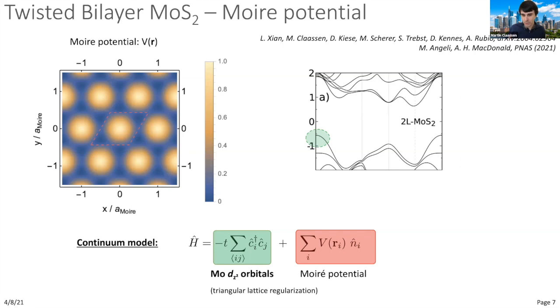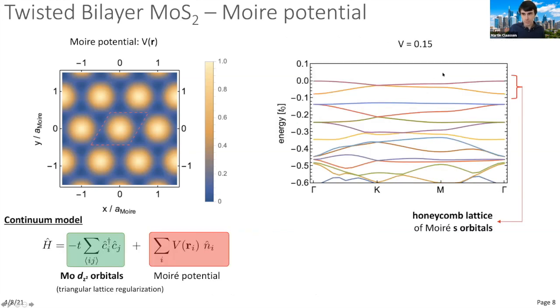This gives a route for more interesting things: what happens with more bands, and what happens when the potential is not scalar but matrix-valued or non-Abelian? For the scalar potential case—this was proposed in the context of cold atoms with optical lattices—as a lattice regularization of a continuum model, increasing the long-wavelength moiré potential strength forms minima on a honeycomb lattice. Electrons localize at the honeycomb sites, forming a series of moiré mini-bands, notably at the top just a regular honeycomb lattice of s-type moiré orbitals.